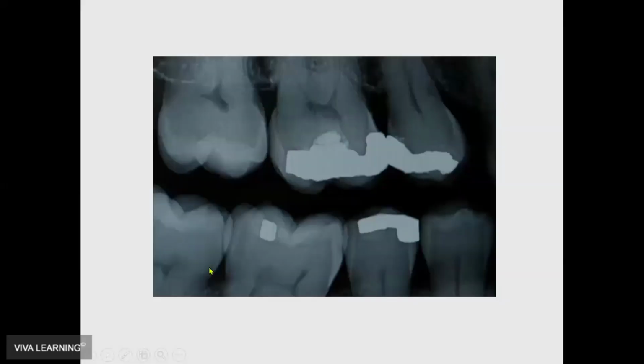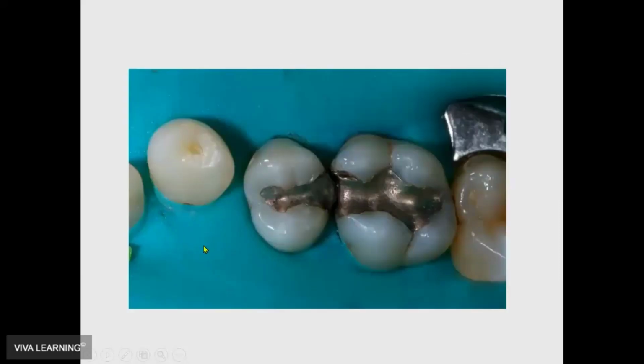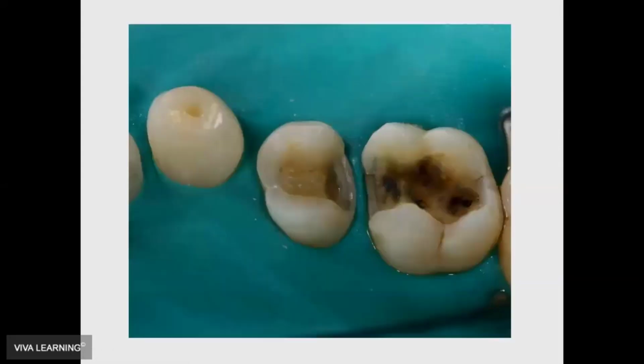This is a case I did, and you're going to see existing amalgams, and this will be a caries. What you see here are failing amalgams. When you take these apart, now you'll see the caries go all the way up to the cuspal tips. Right here, these are funnels, and then you do a beveling right here. You don't leave a butt joint, you bevel this to grab some enamel to seal that interface.